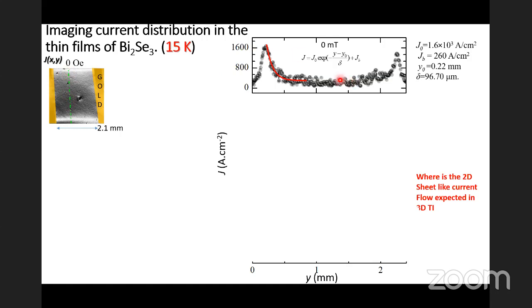So the current distribution, if you recall, the scanning SQUID images also showed that there is a very large amount of currents located on the edges, and there are currents in the center of the sample also. But these are almost like one-dimensional wires, channels of current which are flowing on the edges. So where has the 2D nature of current gone? You should have seen a current sheet which is flowing, but instead of a current sheet, you see wires of current, very strong edge currents which are flowing inside this 3D topological insulator.